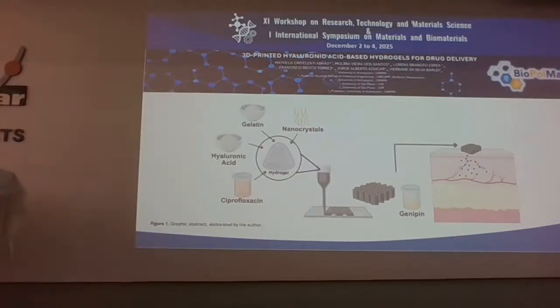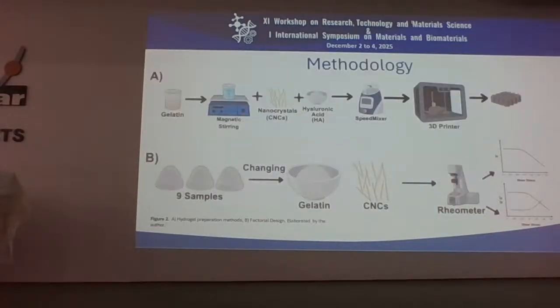The main objective of my project is the development of a printable hydrogel for drug delivery applications, composed of hyaluronic acid, which has good compatibility, gelatin, a natural cross-linker, and cellulose nanocrystals to increase the rheological properties. To prepare my hydrogel, I use a magnetic stirrer to mix the gelatin and a speed mixer to incorporate the cellulose nanocrystals and the hyaluronic acid.